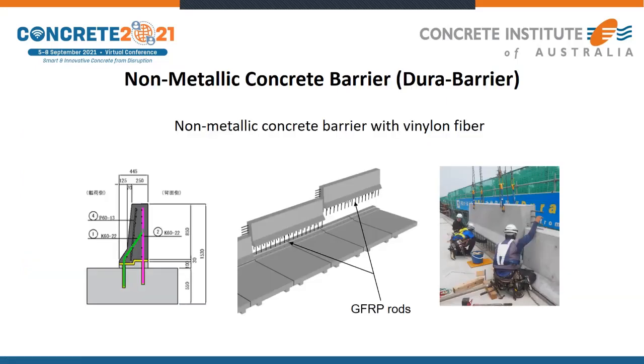At the same time, we use a non-metallic concrete barrier called the Dura barrier. We use GFRP rods because the barrier should carry high impact force. In this case, we use vinylon fiber instead of steel fiber because during winter the highway uses a lot of de-icing salt. So this barrier is the most severe part of the highway, and that's the reason why we use vinylon fiber.